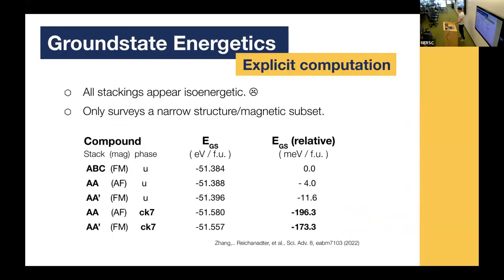So the very first one is just an absolute base ground state calculation of a couple of ideal instances after doing an ionic relaxation of everything. We find that comparing it to the ABC stacked of just one polymorph we had chosen, which is the all up phase shown earlier, that there's a very small difference between ground state energies on the scale of meV per functional unit cell. And so that tells us it reassures us the fact that all these stacking orders are very similar to each other. So it'd be easy to shift them. But the thing that was more fascinating is the CK7. And so this is just a small subset we've taken of a broader sweep of something around 50 different structural polymorphs here. And so the CK7 ones in particular, there are these 2x2x2 unit cells where we very randomly a permutation of different Fe1 sites occupied in an AA structure and an AA prime structure as well. And the observation is that that shows a significant reduction in the energy. So that suggests that there's a significant mixture of the different sites filled in the ground state for the parent compound.